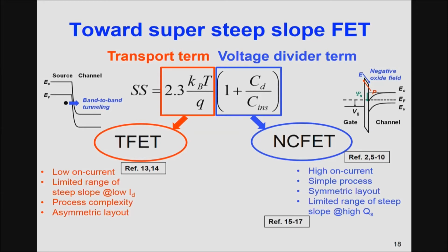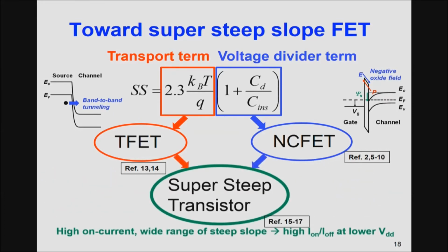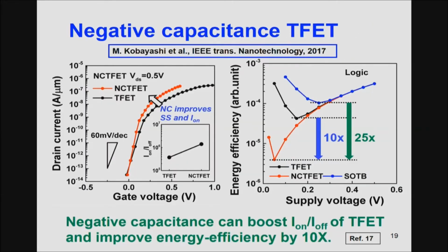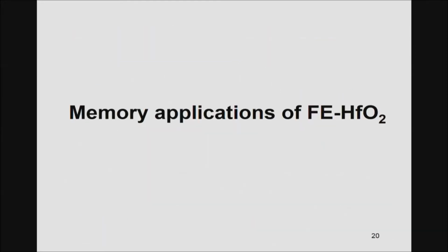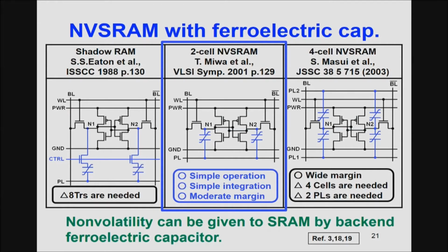So if you can combine TFET and negative capacitance, we should be able to achieve some sort of super steep slope transistor. We did some modeling and simulation of this system. If we can carefully design the NC TFET, the subthreshold slope can be improved over a very wide range of current, and energy efficiency can be improved by more than 10 times. That is great, and it could be the future for the negative capacitance FET. For the rest of the time, let me go through our recent activities on the memory application of ferroelectric hafnium oxide. There are several architectures.